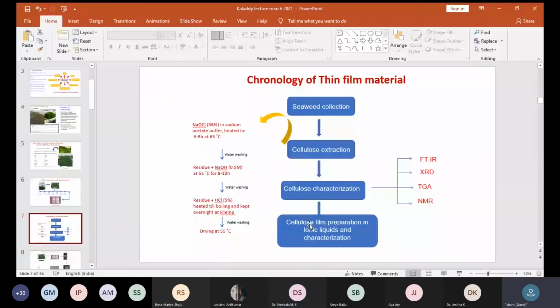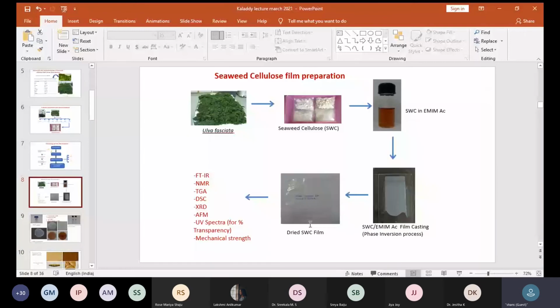So what we do, we make sure the cellulose is matching with the conventional quality, and we try the lab casting, hand casting method, and we prepare the thin film. Then we characterize the thin film. For this, we use ionic liquid because of cellulose solubility; we use ionic liquid of the imidazolium family. So we take the seaweed, we extract the cellulose. This extracted cellulose is dissolved in ethyl methyl imidazolium acetate. This is a conventional ionic liquid for cellulose solubility. Then this slide shows how we cast the food package film. We take the glass plate, we use the doctor blade suitable for the solution. We did everything inside the fume hood, and the ambient condition and relative humidity we maintain.